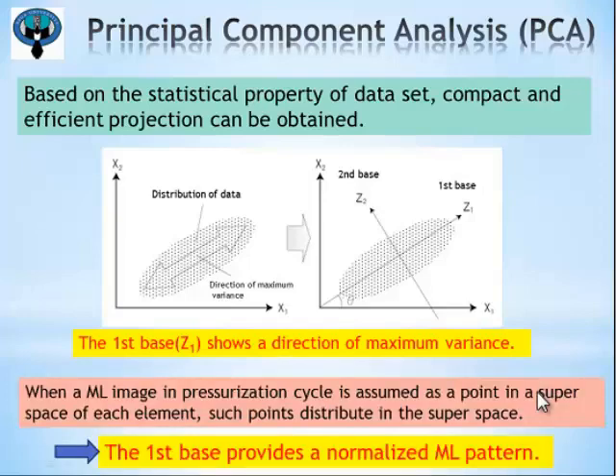Then ML image in pressurization cycle is assumed as a point in a superspace of each element. Such points distribute in the superspace according to the pressure value. As a result of PCA, it is expected that the first base provides a normalized ML pattern because variance due to the pressure is larger than that of noise. We examined our idea with experimental data set.